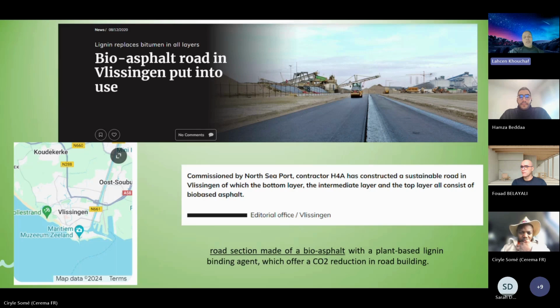In order to give you some examples of previous valorization, for example, in road, here we can see a road section made of bio-asphalt with a plant-based lignin binding agent, which allows a CO2 reduction in road building. It's developed in Vlissingen in the Netherlands. This project is commissioned by North Sea Port contractor H4A, which has constructed a sustainable road in this region, of which the bottom layer, the intermediate, but also the top layer all consist of bio-based asphalt from lignin.